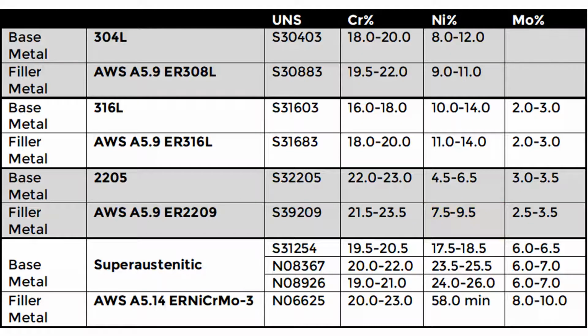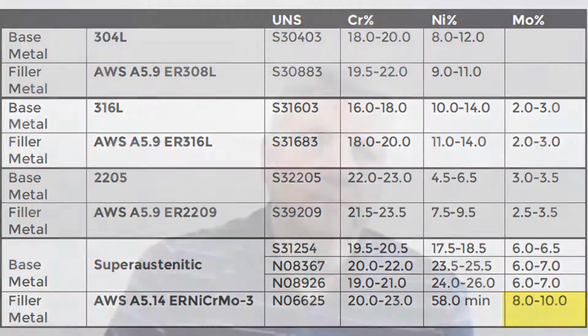Longitudinally welded 2205 pipe, produced in accordance with ASTM A789, are autogenously welded, but are annealed after welding to restore the optimal duplex microstructure. Similarly, the filler metal for welding superaustenitic stainless steels is significantly overalloyed with molybdenum. This higher molybdenum content compensates for the significant segregation that occurs with these highly corrosion-resistant stainless steels. Otherwise, the segregation resulting from autogenous welds would significantly reduce the corrosion resistance of the weld metal.